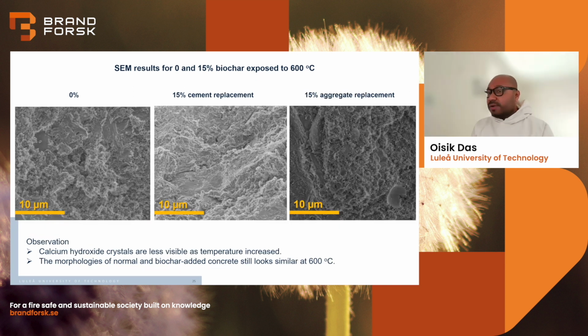Now we see what happens to the concrete samples when they were exposed to 600 degrees centigrade. We see a few changes. The first change we see is that calcium hydroxide crystals, which were present at lower temperature, are less visible in all three samples. But still, the morphology between the samples, so the standard concrete, the cement replaced sample and the aggregate replaced sample, the morphology and the microstructure look quite similar.